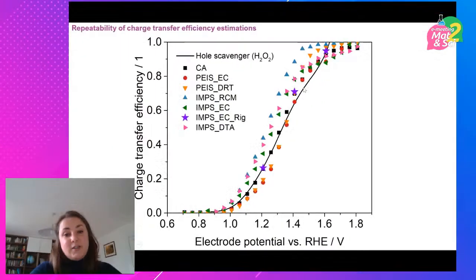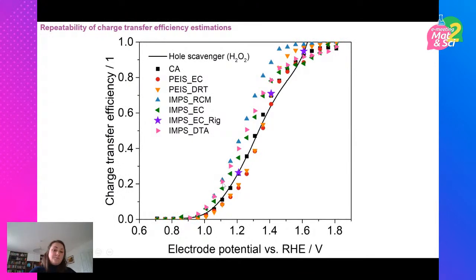But if you are really trying to compare one material against the other, you really need to know your material very well and your technique very well, and use multiple samples to be confident that the technique you're using is giving reliable values. So what Frankie concluded, that actually chopped photocurrent measurements are probably the most reliable measurement, and that using sacrificial reagents actually introduces more error than is apparent from the results that actually look very neat at first